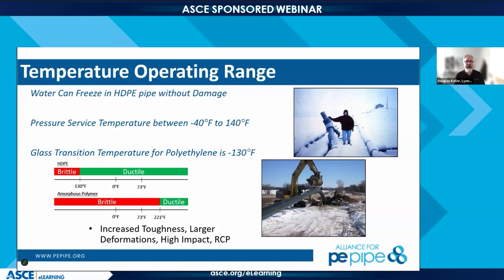Unlike some of the other plastic materials, for example, an amorphous polymer is actually in its brittle state at room temperature. An amorphous would be a PVC material. So that's why you can put a hammer to polyethylene, but you don't want to put a hammer to PVC. Dave? So the question comes up at what temperature can we actually perform butt fusion and join these pieces of